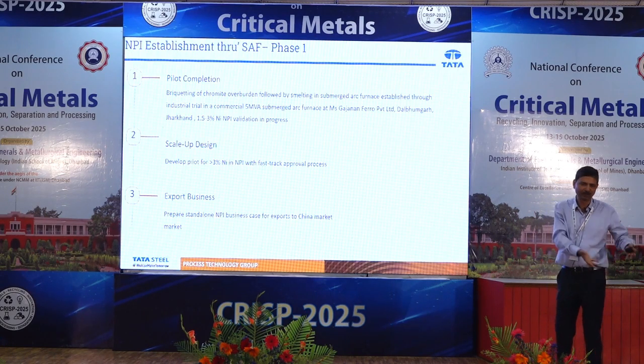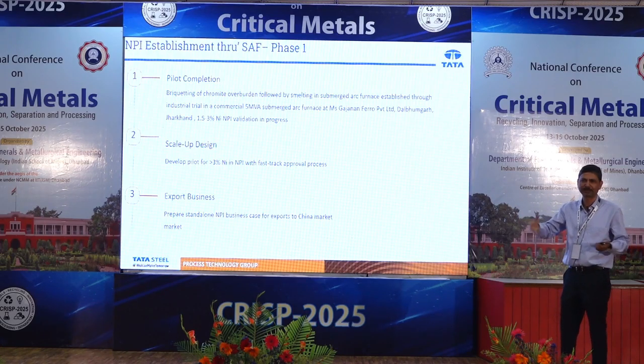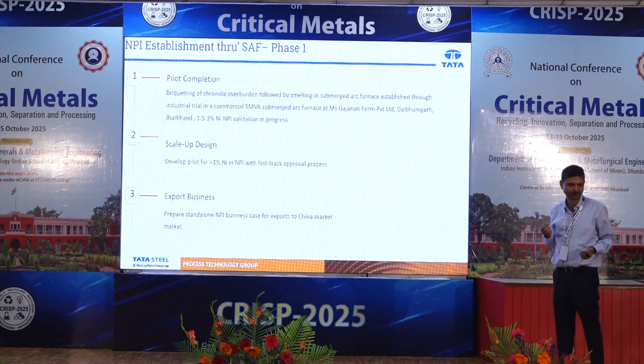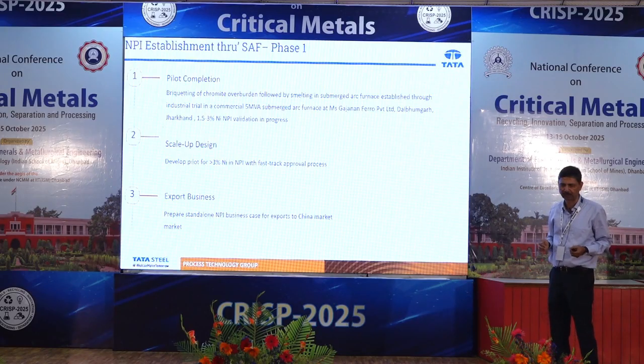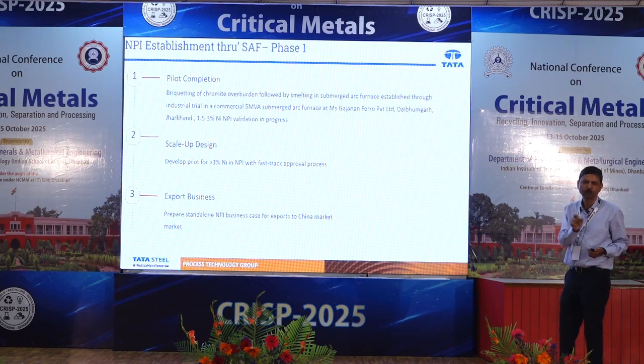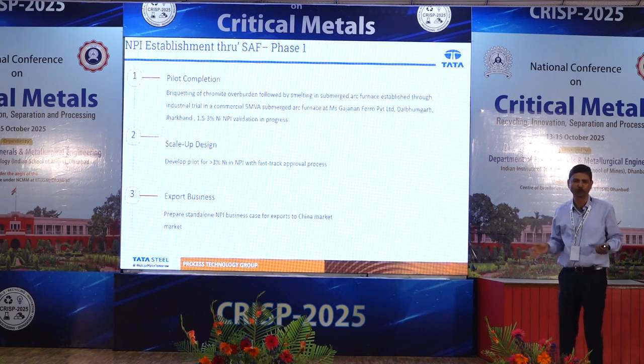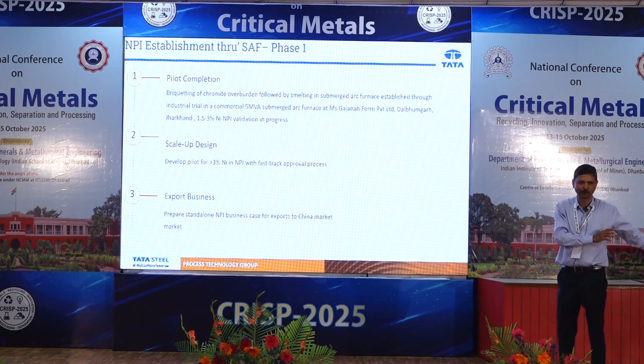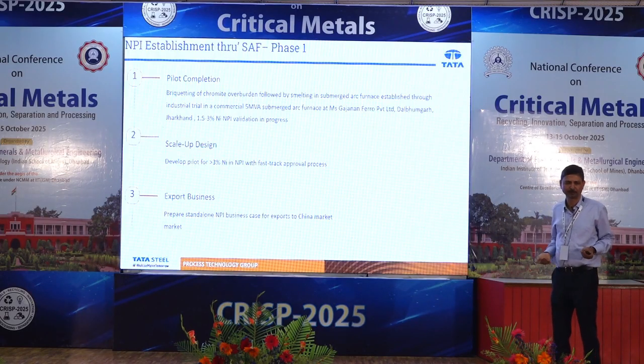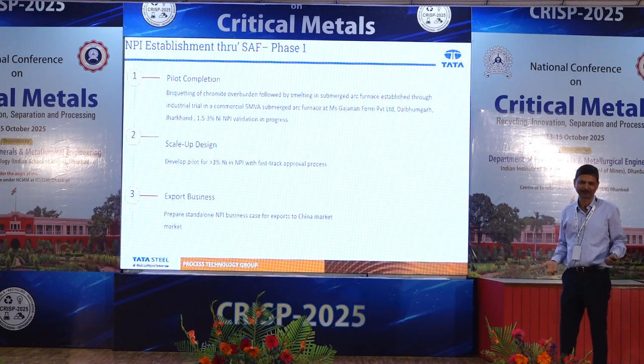And if you have nickel pig iron material, the normal stainless steel lowest grade is 2 point something nickel, and higher grades are 8 to 10 to 16. So there are no users for this 2%, and then the cost of manufacturing you could not recover. The tons of material you have produced are still lying at our place. We could not sell it. We are getting 30,000 to 35,000 rupees a ton for that material, which is near the pig iron price. So we could not take it forward.